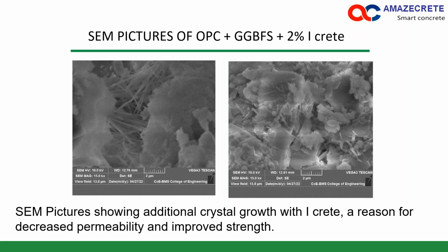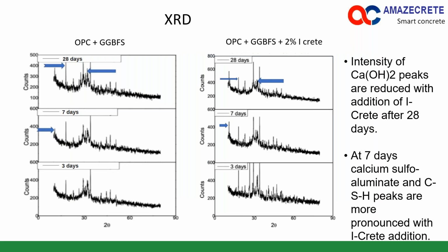And if you go to the next slide, please. There is a clear-cut intensity drop if you look at somewhere around 20 or 25-degree angle, at 28 days. If you look at the intensity counts there, the intensity height is substantially lower with iCrete than without iCrete. What it means is that the extra Ca(OH)2 that is produced is consumed in forming an additional binding phase. This is one inference you can come to. And at 7 days also, around the same 10 degrees angle, the intensity of the sulfo-aluminate peaks is higher with iCrete. Yes, madam. Thank you.